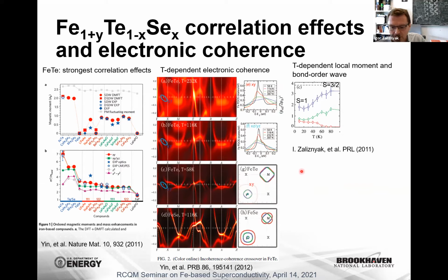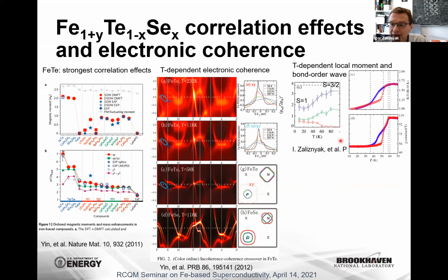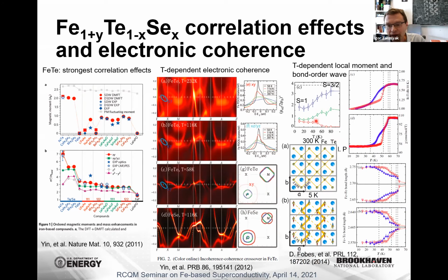And this was consistent with the measured resistivity, which became more metallic, corresponding to the appearance of conduction electrons, and the decrease of magnetic susceptibility, illustrating the decrease of local moment magnetism. We later discovered that this transition is actually accompanied by the formation of a bond order wave made of zigzag ferromagnetic chains. So this is a sort of orbital order that develops when electrons become coherent. This order, by the way, explains the double stripe magnetic order as the order of antiferromagnetically coupled ferromagnetic zigzag chains, similar to the situation in manganites.